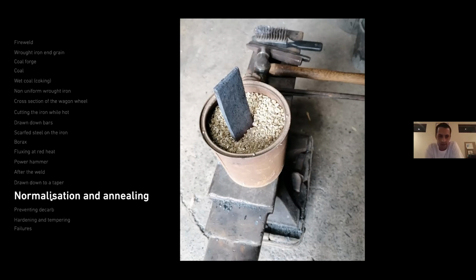So normalizing, which is bringing it up to the critical temperature and slowly letting it air cool, is incredibly important in this sort of blade to be able to quench it and maintain any kind of flatness. It really curves a lot. It can curve like 6 millimeters in the center over maybe a 200 millimeter length blade.